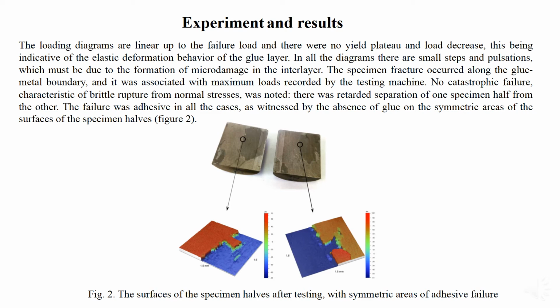The specimen fracture occurred along the glue-metal boundary, and it was associated with maximum loads recorded by the testing machine. No catastrophic failure, characteristic of brittle rupture from normal stresses, was noted. There was retarded separation of one specimen half from the other. The failure was adhesive in all cases, witnessed by the absence of glue on the symmetric areas of the surface of the specimen halves.